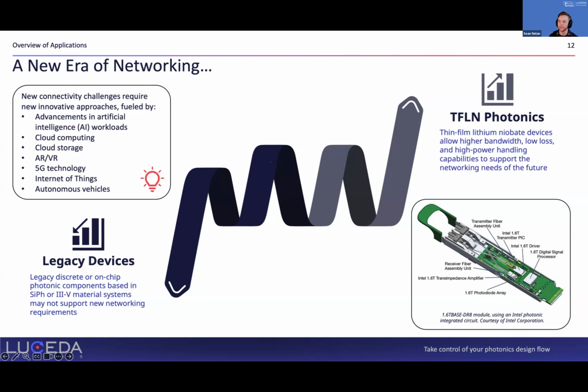Now with the onset of TFLN, or thin layers of lithium niobate, which we could put on a silicon photonic chip or order devices from a foundry, we can achieve very high speed modulation up to, in some cases, a terahertz, but more commonly for these sorts of systems, 100 gigahertz, 200 gigahertz, to enable what I would call the networking needs of the future. High-speed operation for chips that replace existing chips in telecom and datacom centers, in other words.